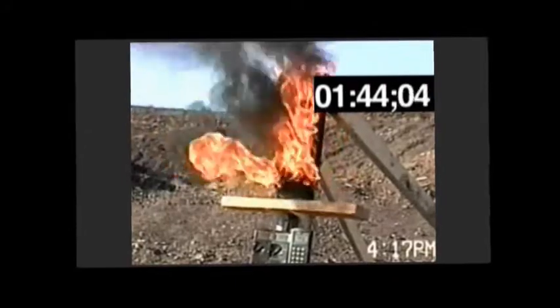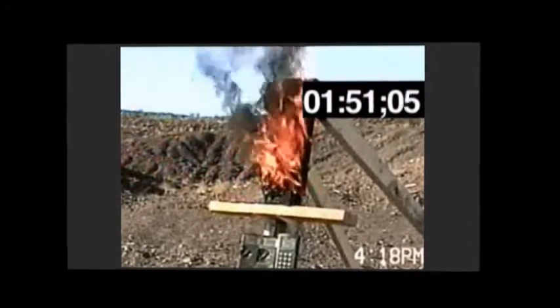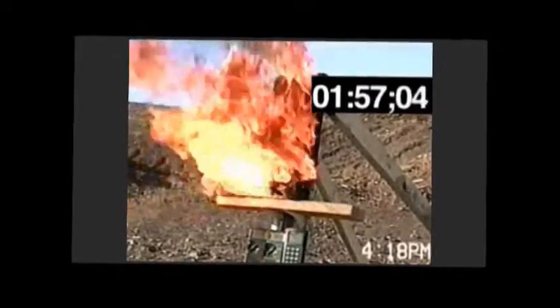This creates extreme temperatures — again, over 700 degrees Celsius — sustained for over 4 minutes. Each successive cell breaks down, combusts, and aided by the release of oxygen, continues the propagation.